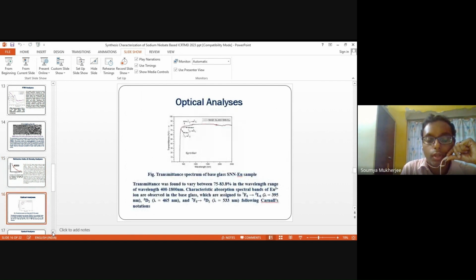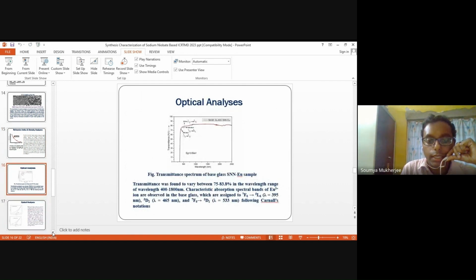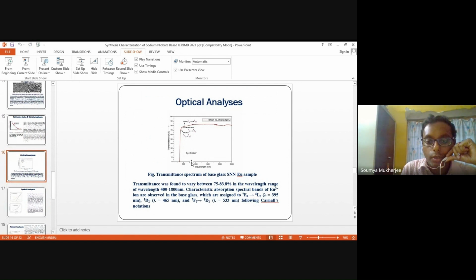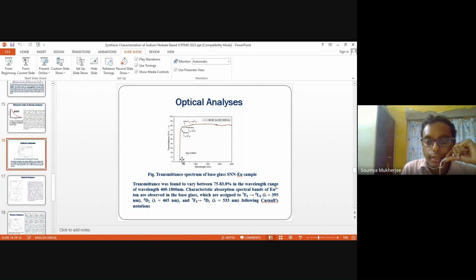Now we have also calculated the optical transitions, and it is carried out with the help of the transmittance spectrum, using UV-Vis-NIR of the sample, in the range from 400 to 1800. The transmittance is quite close to 75 to 84% in this wavelength region, and these characteristic absorption bands are noted, which are assigned to the transitions 7F0 to 5L6 and 7F0 to 5D1, following Carnall's notations.